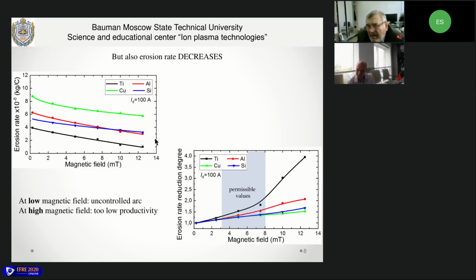And the degree of erosion rate reduction is drastic for titanium. Here you can see the erosion rate decreases up to 4 times with increasing magnetic field from 0 to 12 millitesla. For other materials, the erosion rate reduction isn't so drastic.